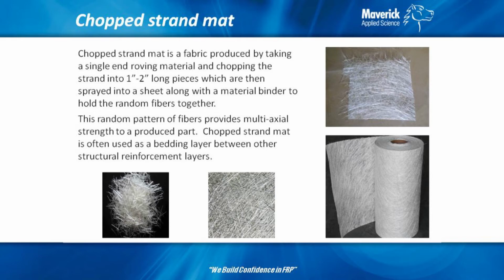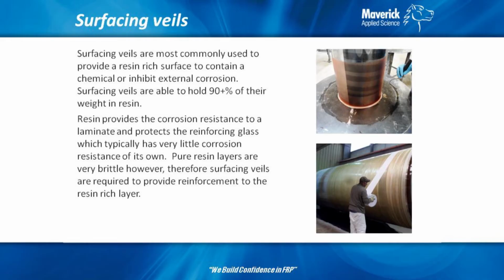Woven roving layers typically do not do well back to back with each other. You need some kind of a bedding layer in between them to separate them a little bit. So what you'll see is chop strand mat used for that, in addition to just being, again, the primary structural reinforcement for a vessel or a flange. You'll hear that called type 1 when it's only chop strand mat. There's a lot of standard developed procedures out there for type 1 mat. Thicknesses are known. It's a very well-known commodity.